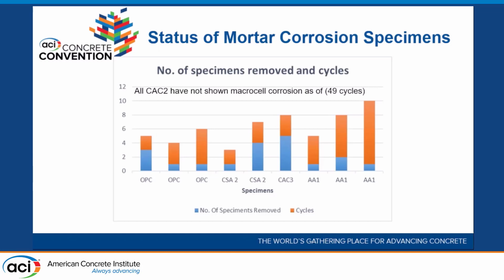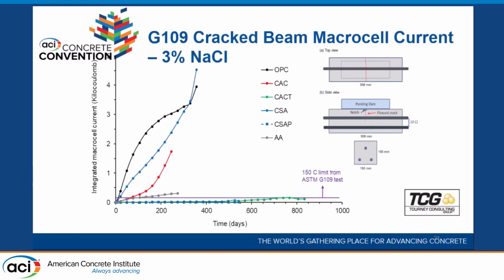Basically, the blue number is how many we pulled out, and this is what cycle. So at 5 cycles, we pulled out 3, I think that's it. Oh, there's the cycles, at 5 cycles we pulled out 2 of them, and going along the line. There were 10 of each, but we'll get back into this a little later. With the cracked beams, these were large beams, basically 6 by 6 by 22 or so inches, and we measured the macrocell corrosion occurring on these.